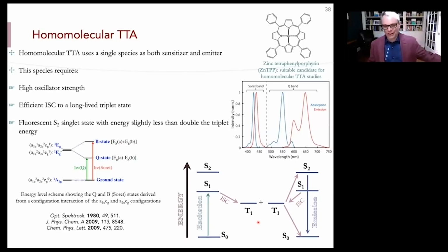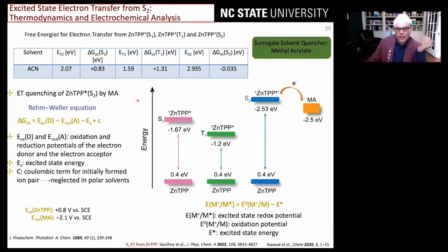And that's why the zinc compound doesn't do it, because the zinc compound doesn't self-quench and it doesn't annihilate with other zinc compounds because of the way we do the experiment. But anyway, let's put the energy level picture on this. These are the potentials of the zinc TPP singlet and triplet.